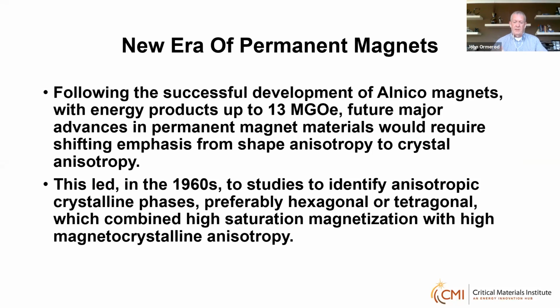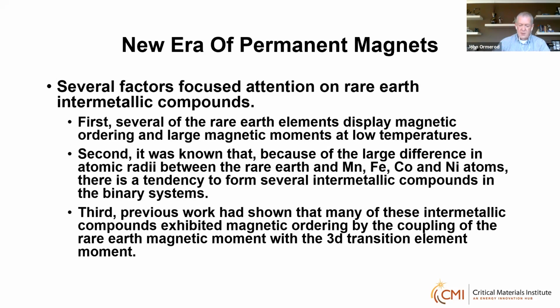However, it became apparent to both industrial and academic researchers that any future major advances in energy product would require increases in coercivity past what could be achieved by shape anisotropy. And so this led to a shifting emphasis to crystal anisotropy. In the 60s, the search began to identify uniaxial compounds that combined high saturation magnetization with high magnetocrystalline anisotropy. The rare earth intermetallics were of particular interest because it was well known that the rare earth elements displayed magnetic ordering and large moments at low temperatures. The rare earth elements also tended to form intermetallics with the 3d transition metals, and there was a strong coupling of the rare earth moment with the transition metal lattice.